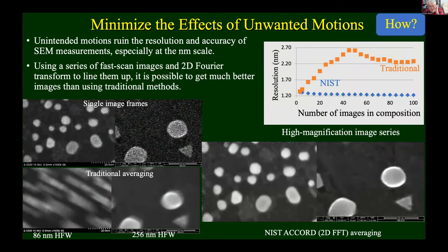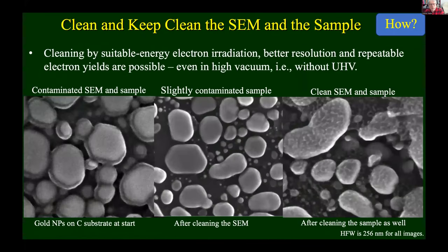So I would like to say a few words about how we do it. One is to get rid of the detrimental effect of drift. This is what you can see if you do fast images and just add them together. But if you use two-dimensional Fourier, then you get much better quality images. You can compare this here. This was developed here at NIST by us and then later implemented in any SEM that you can find today.